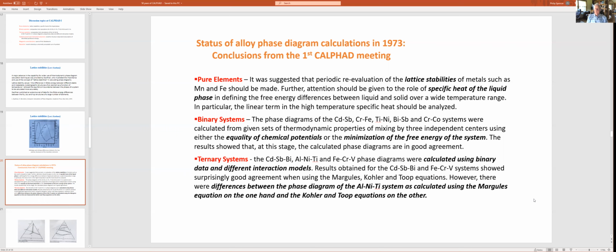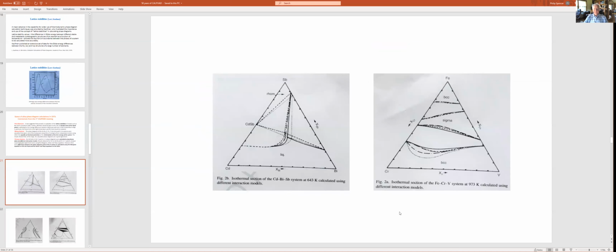The results obtained for cadmium antimony bismuth and iron chromium vanadium showed surprisingly good agreement using whether it was the Margules, Kohler or Toop equations. However, there were differences between the phase diagram of the aluminium nickel titanium system, calculated using the Margules equation on the one hand, or the Kohler and Toop equations on the other. Here are, for example, the results obtained for cadmium, bismuth, antimony, the various interpolation equations. Not a great deal of difference. Iron, chromium, vanadium, a little more difference, but still the same general phase boundaries obtained.